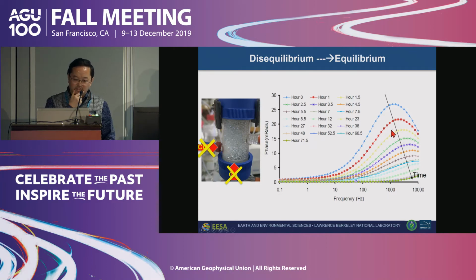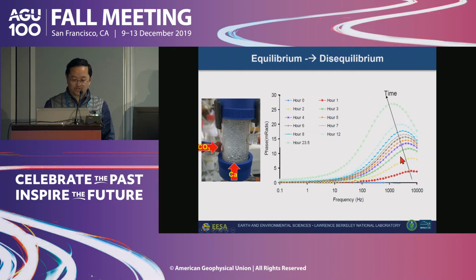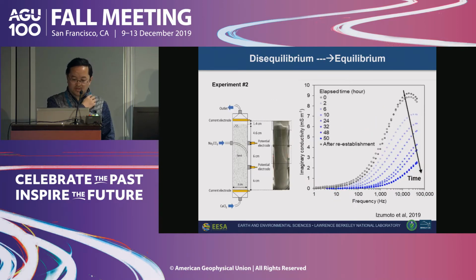What's interesting is we observed that when you turn off the calcium and carbonate injection, which allows the system to fall back to equilibrium from this disequilibrium condition, you have a very rapid decrease of the signal and also a shifting of the peak from low to high. Within a few hours, if you start the injection again, the signal quickly goes back up. This back and forth can be controlled, and it's really repeatable. This is a repeated observation, not only in our data a while ago, but also in a recent experiment done in Germany using different media and different setups. So this demonstrates the repeatability of this observation.